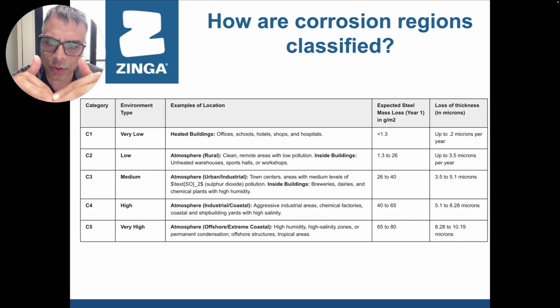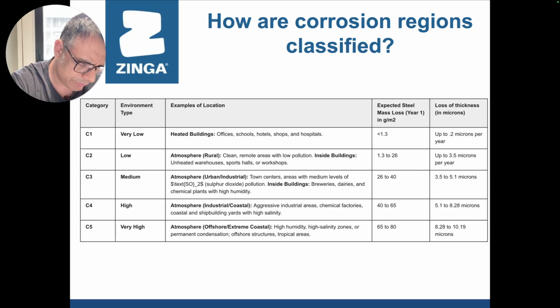C2 is low, not very low but low, where it's a rural atmosphere, clean remote areas with low pollution, inside buildings, unheated warehouses, etc., where the steel mass loss is 1.3 to 26, and you lose up to 3.5 microns, either of the galvanized coating or of the parent metal. One of them will go. Now starts the problem where C3, C4, C5 are there, where sulfur dioxide pollution takes place in urban and industrial environments, in breweries, dairies, distilleries, where up to 5 microns a year thickness is going.